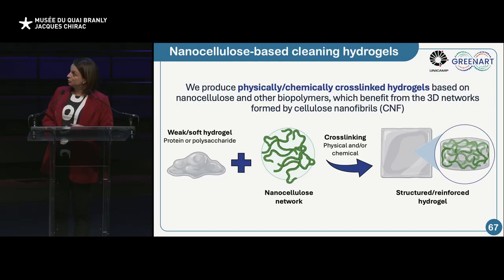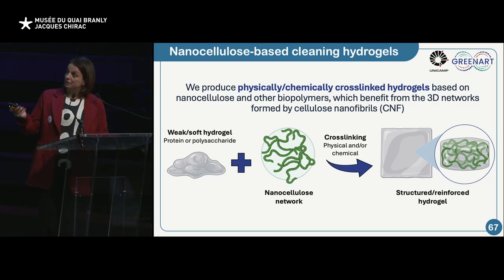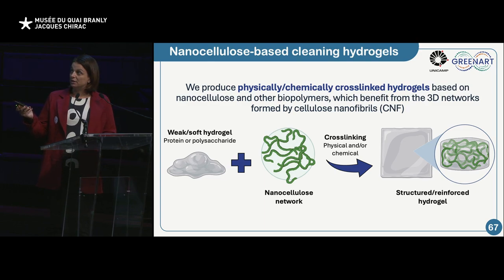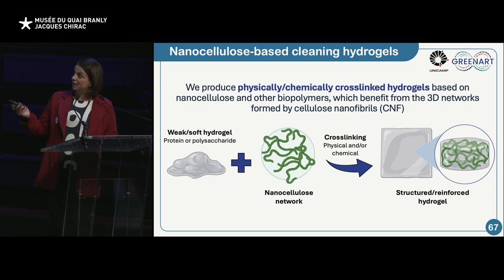So what we produce in the lab are physically or chemically cross-linked hydrogels based on nanocellulose and also on other biopolymers, which will benefit from the 3D network formed by cellulose nanofibers. So we prepare these soft gels containing proteins or polysaccharides, and then we incorporate the nanocellulose network, and we cross-link this nanocellulose network using these physical or chemical bonds. And we will be playing with this structured and reinforced hydrogel.